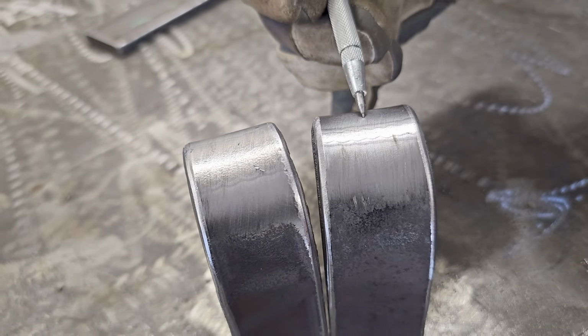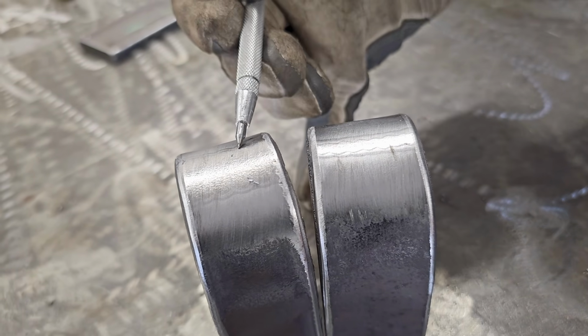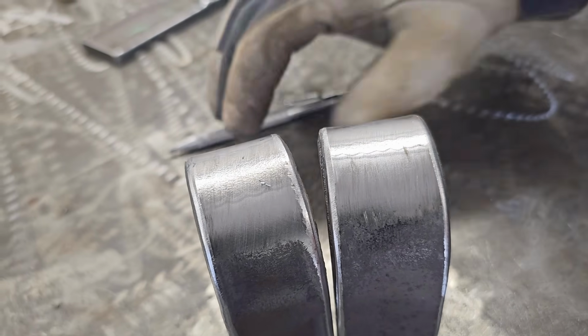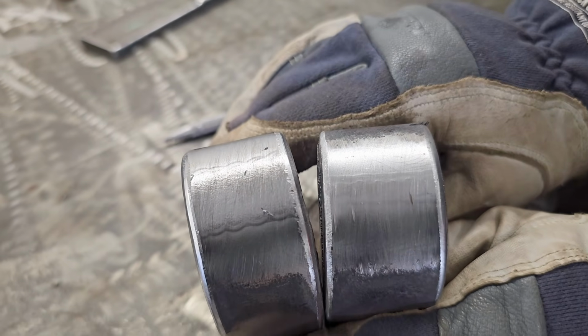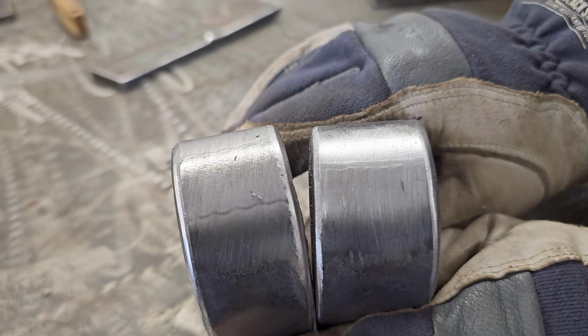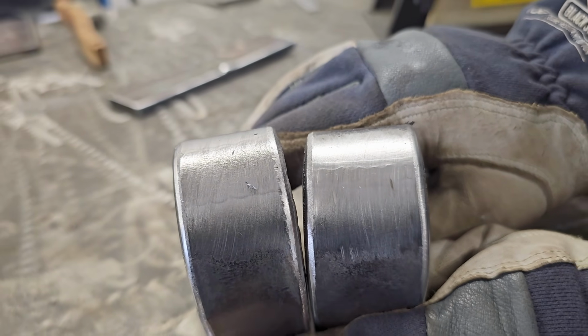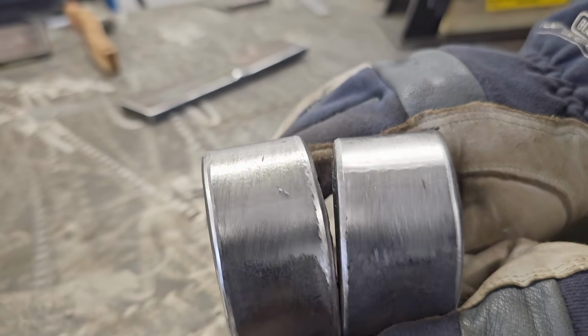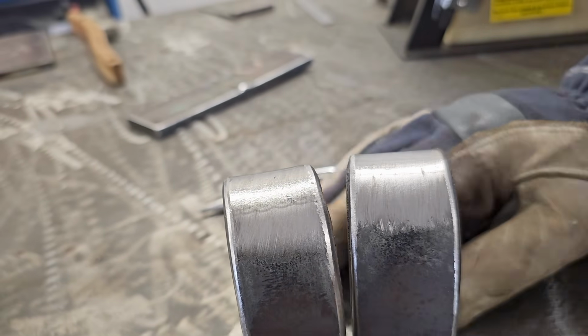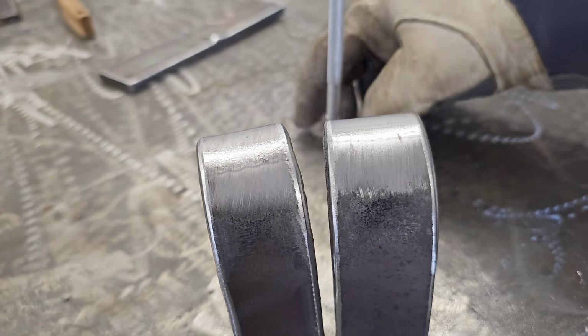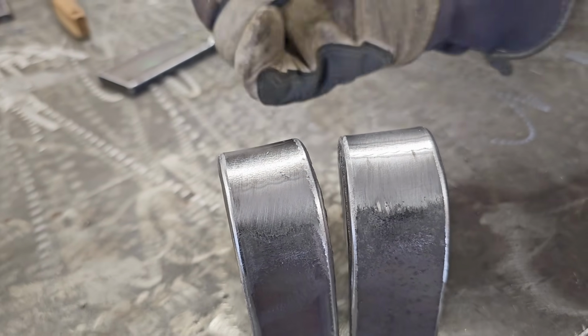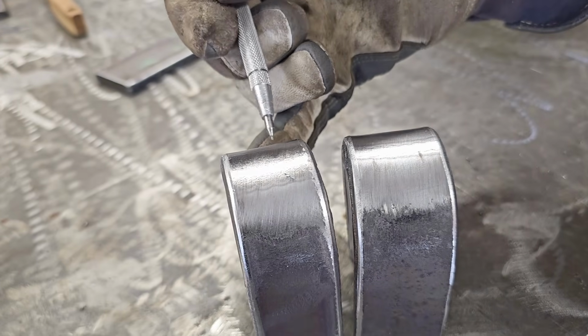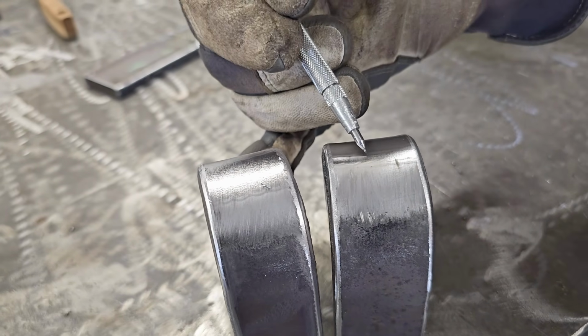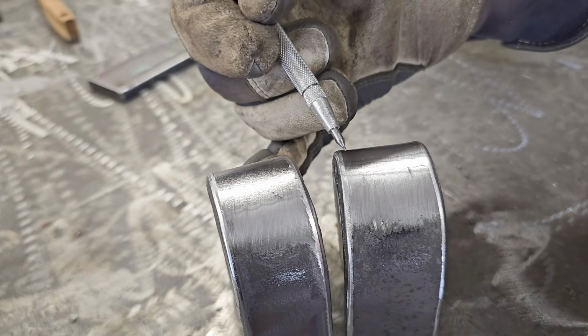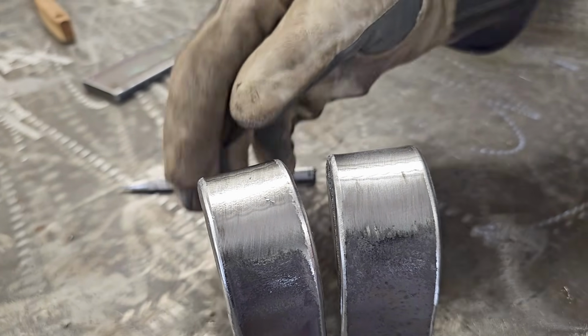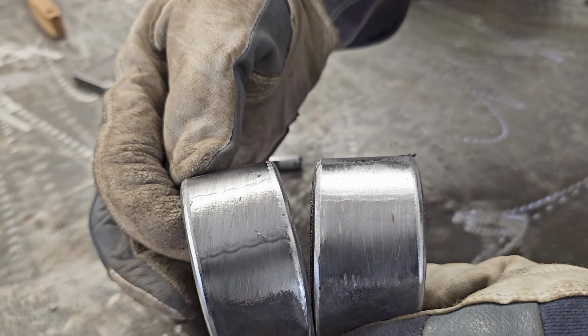All right, so here we have our root side bend test and our face side bend test. And you can actually see the weld metal pretty clearly if you do a good polish job. It has a different grain structure than the base material, so you can see it pretty clearly as it stretches out there in the bend test. And the AWS D1.1 code says if any discontinuities open up in the bend test, they can be no more than 1/8 of an inch measured in any direction. So we really didn't have anything that opened up on these bend tests.